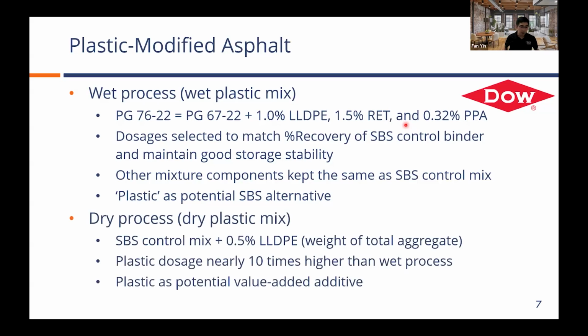For the dry process mix, it's a little bit different approach. After discussing with our sponsors, there was interest in looking into adding recycled plastic using the drop-in approach. So basically, we did not do any other modifications from the control mix. All we did was add 0.5% of the linear low density polyethylene pellets that I showed you on the previous slide into the mixture during production, and see what happened to the mixture performance. So if we see any difference, we can attribute that difference to the addition of this 0.5% linear low density polyethylene.